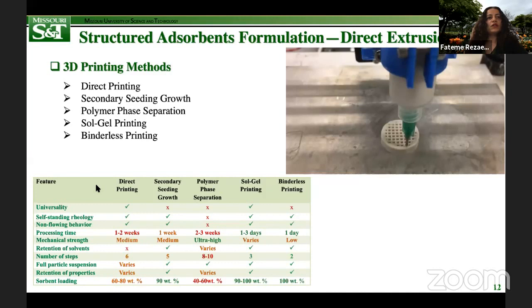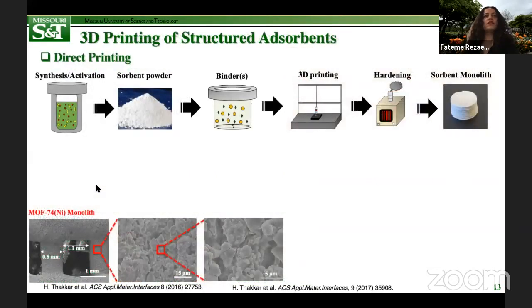Polymer phase separation is great for delivering robust structures with ultra-high mechanical strength. In terms of the retention of solvents, it varies among these different techniques, but most importantly, if you consider number of steps, you see that sol-gel printing and binderless printing are advantageous over the other techniques. And in terms of adsorbent loading, most of these techniques, except polymer phase separation, deliver structures with high loading, in most cases greater than 80%. All right, now with that, let's start discussing these techniques one by one.